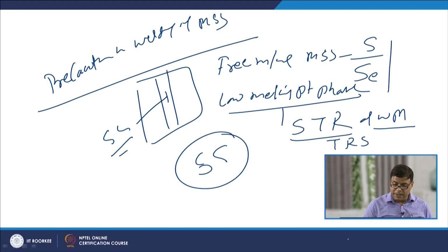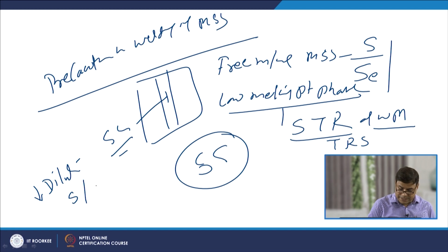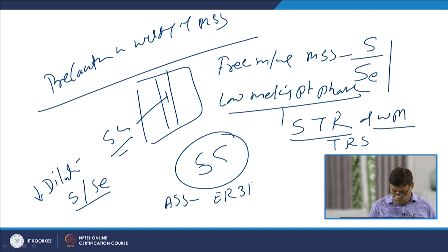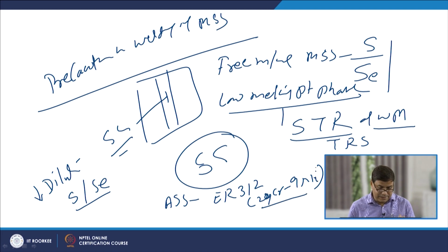So, the best way is to reduce the dilution so that the minimum amount of sulfur and selenium goes into the weld metal. At the same time, use an austenitic stainless steel filler like, say, ER312, having 29% chromium and 9% nickel. This helps in reducing the cracking tendency of the martensitic stainless steels of the free machining type.